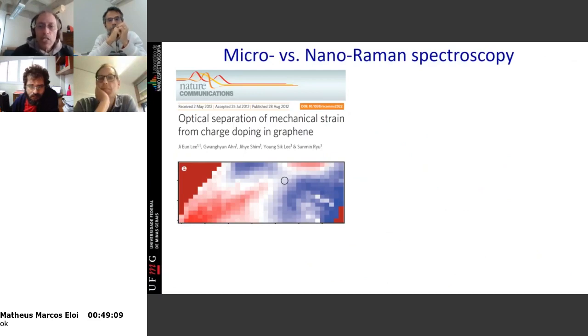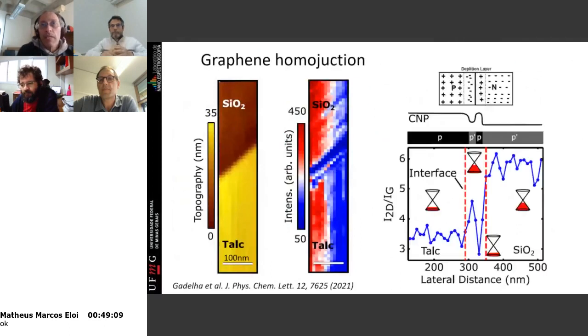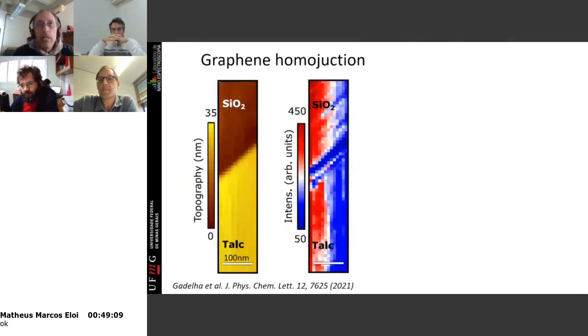However, if what is changing the frequency is strain and not doping, the slope of the plot of one frequency versus the other is different. So what he demonstrated is that by looking at the slope of the change in frequency, you know if this is strain or doping, or both, if things go into the middle. And what we were able to demonstrate here, and this is what I didn't go into detail, is that what is generating the change here is doping and not the strain.